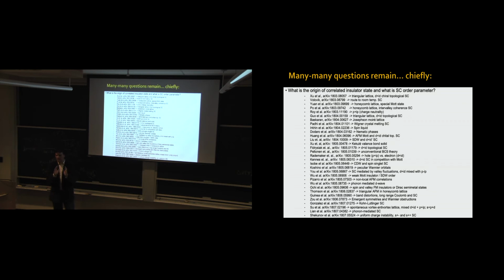All of these experiments have been done in turbostratic graphite, where the graphene planes have small angular misorientations between the layers. When you have that, you can calculate this will result in flat bands in the electronic structure of graphite. Put your chemical potential in those flat bands, and you get correlated superconductivity with very high critical temperature. As I was reading this, I was like, oh wow, oh wow, each page was like whoa. So he said finally someone has done the controlled, reproducible experiment. Now just add a few more layers and get room temperature. Just start right there. So he encouraged us to try.